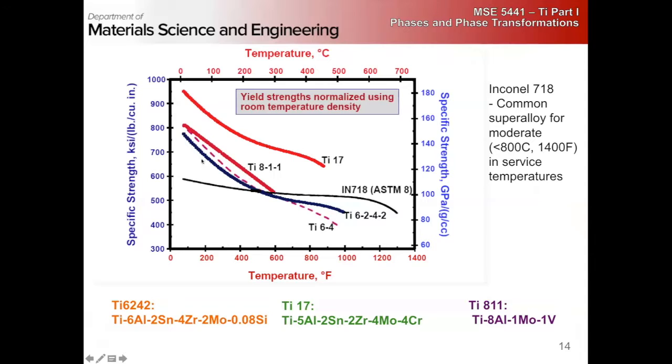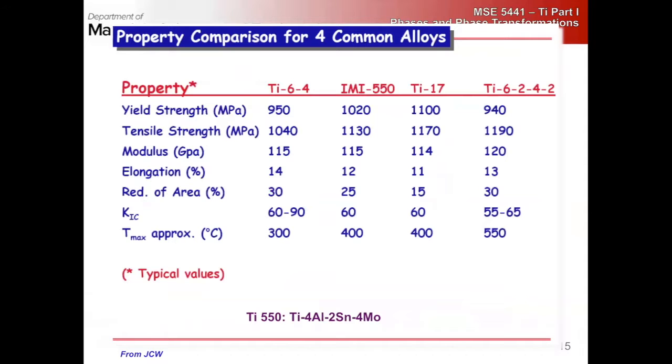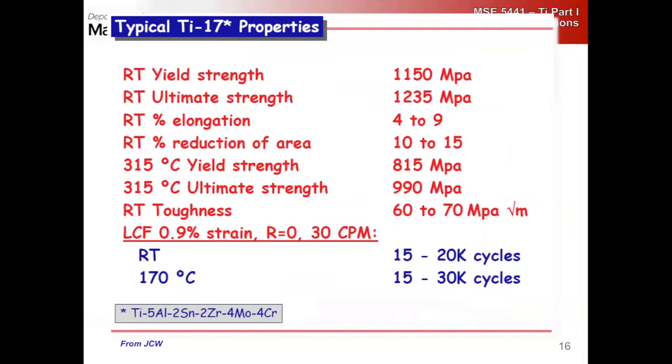You can have higher initial yield strengths in titanium alloys, but they lose their strength with temperature much more rapidly, whereas superalloys have this anomalous strength behavior where they keep their strength out to much higher temperatures, right? And why that happens is a major section for discussion in the coming stuff. Right, so just properties of different things, just for your reference.